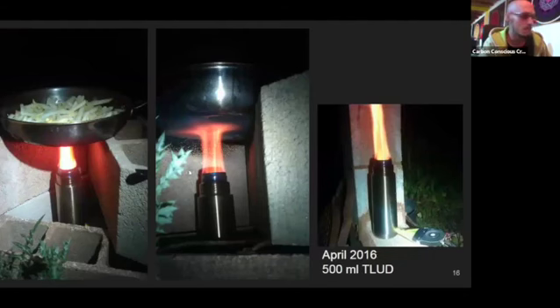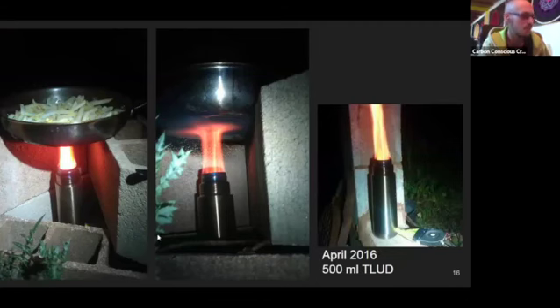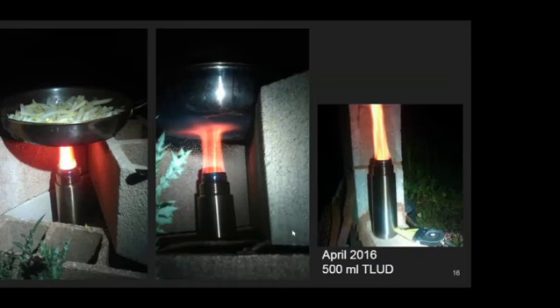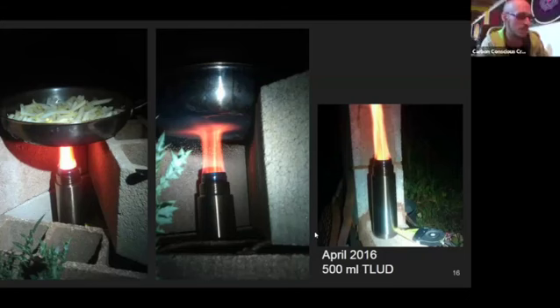And so I went from a very big gasifier, then I was thinking, oh, I've gone big, and I didn't want to go any bigger. So I thought, let's see how small I can go. So I built a very small gasifier from a thermos flask that was 50 centiliters, half a liter. And because of this small size, I was restricted to the use of stove pellets, because any other fuel just doesn't have the energy density to make use of the fire. And because the stove pellets are quite dense, there was also the necessity for a small ventilator to make sure that there was enough oxygen for a clean combustion.